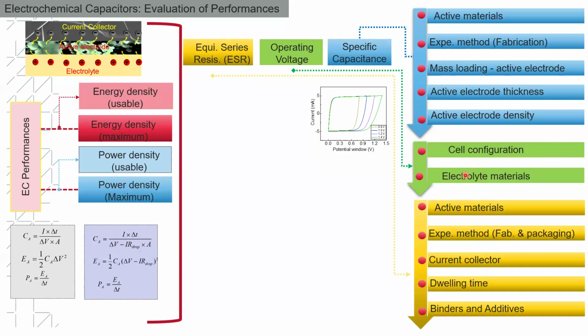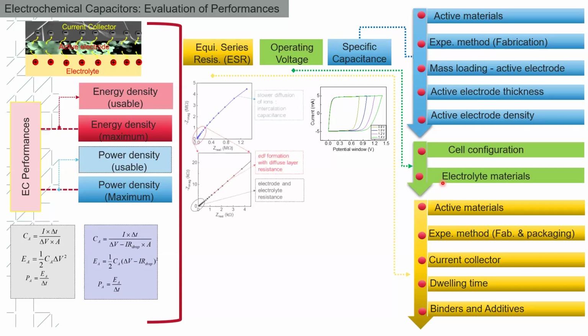Okay, and one of the important parameters in supercapacitor performance evaluation is the equivalent series resistance, where voltage drop or power loss can happen. Here you can see that it depends on various things: the type of active material you are using, the experimental method like packaging or fabrication approach, the current collector, or the dwelling time, various parameters which can influence the equivalent series resistance. When the equivalent series resistance is very high, the power loss will be very high, or the voltage drop will be very high.